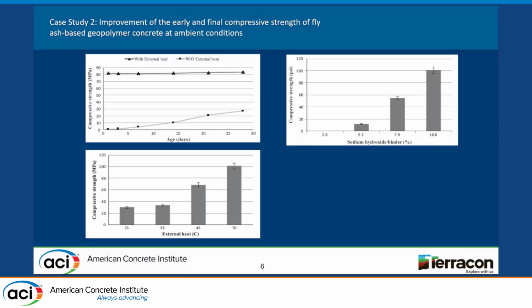So then I wanted to see also the effect of the sodium hydroxide concentration. How about if we reduce the sodium hydroxide concentration? The sodium hydroxide has a high energy consumption, and also is expensive. So I wanted to see how about if we reduce it, and you can see here, once I reduce it, the compressive strength really reduced drastically. So I found out there is two main things in this compressive strength, which is the external heat, the concentration of the sodium hydroxide.